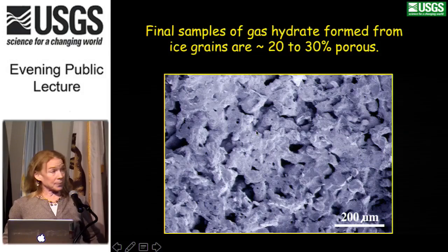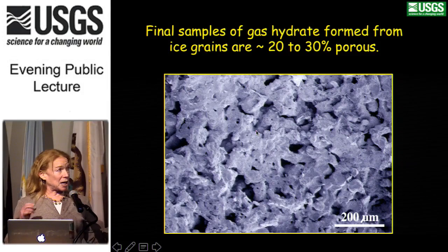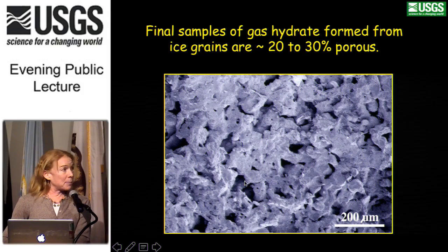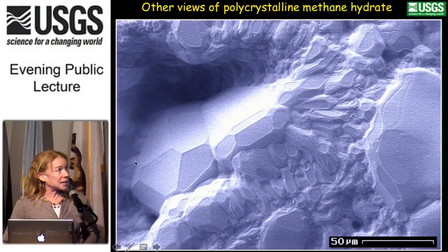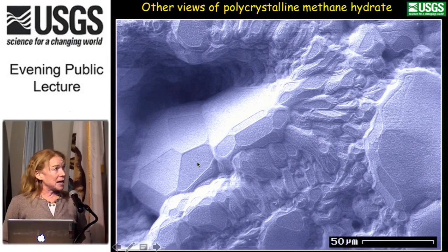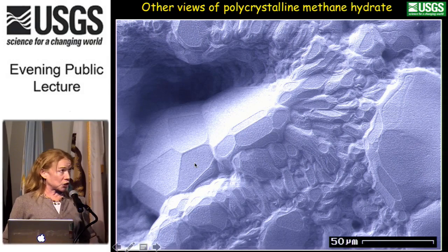When we look at a sample just in a lower magnification, we see a lot of porosity in them because there's originally all the space between the ice grains. It looks even more porous here because there's some grains plucked out. But along those cavity surfaces, again, we see the beautiful crystalline formation here. In our old scanning electron microscope, it's higher vacuum that created this pitted look on the surface.